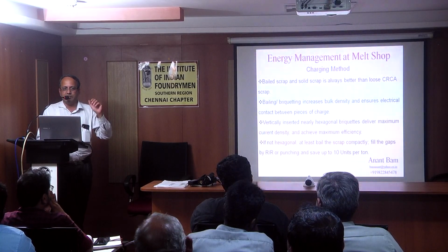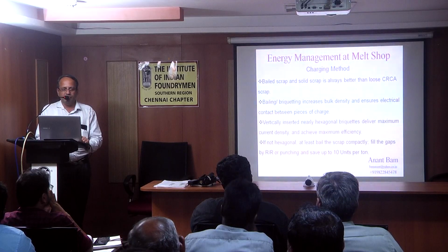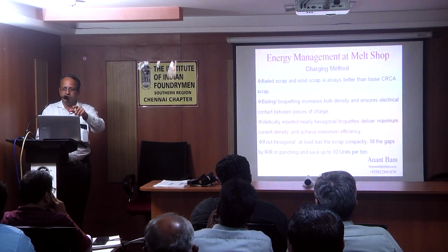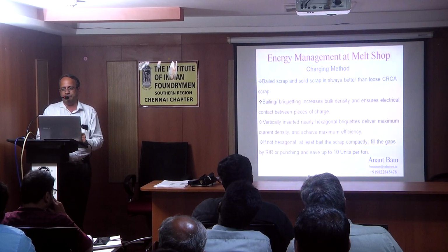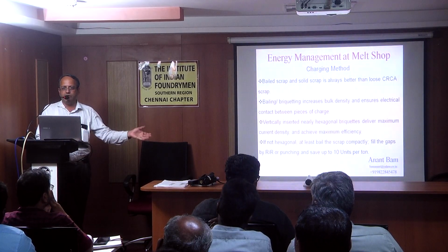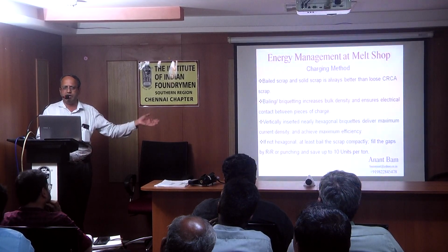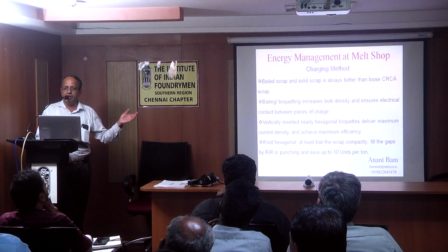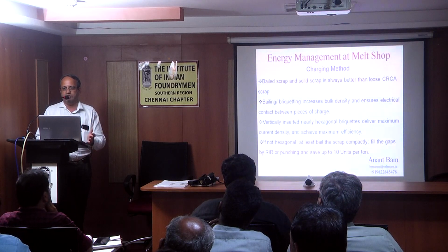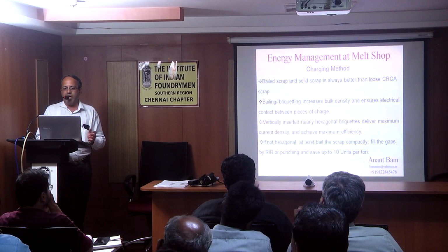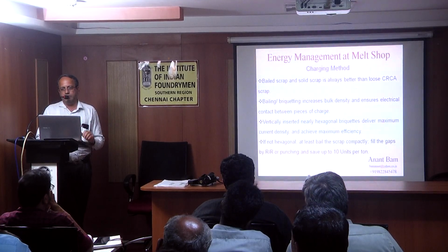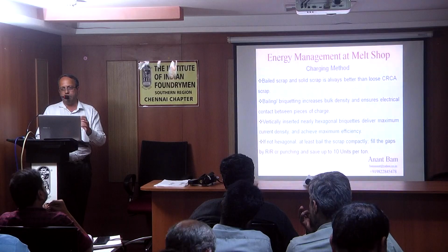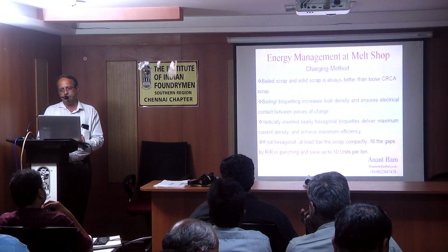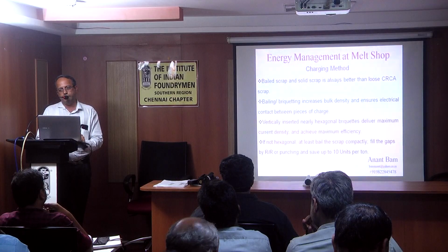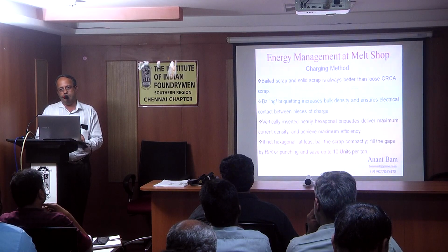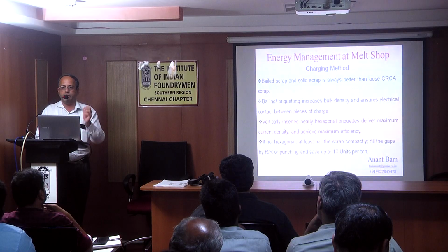The density of cast iron is 7.6, 7.7. So multiply that envelope volume by that density, and you will get the ideal weight required. And you have got a weighing scale on the melting platform. Just weigh that casting, and then you will realize how much space you are wasting. Go as close to the density of cast iron as possible in your scrap contents. That enhances the efficiency of the induction effect and reduces energy consumption to a very great extent.